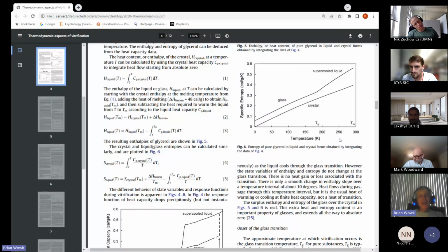As a practical matter, the Kauzmann temperature is so much lower than the glass transition temperature, typically 20 or 30 degrees below it, that you're probably safe at that temperature, even against ice nucleation. But I think that's kind of a coincidence. I don't think the theory of the Kauzmann temperature or the Kauzmann paradox is what confers that stability.